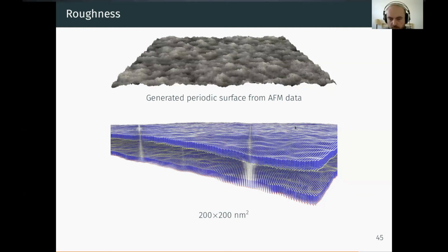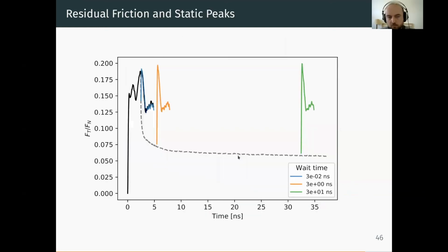Now, of course, I need to have roughness in the system, and I used directly the roughness data that was given to me from the experiments. I used it to generate periodic surfaces, and I included this roughness into my molecular model. So at the end, I have a model that is about 200 nanometers by 200 nanometers, and I can compute my friction force. So what I do is essentially the same protocol as in the experiment. I have an initial sliding phase. So there's some noise here. This is inherently due to the roughness of the surface.